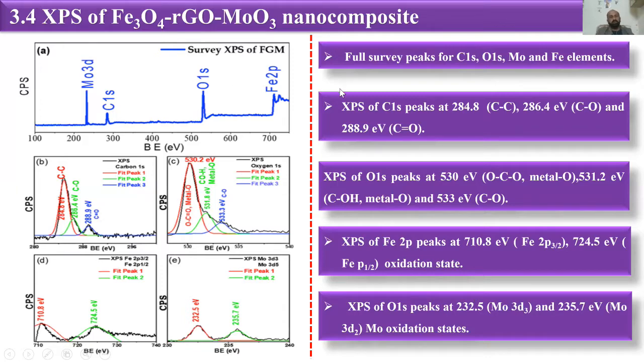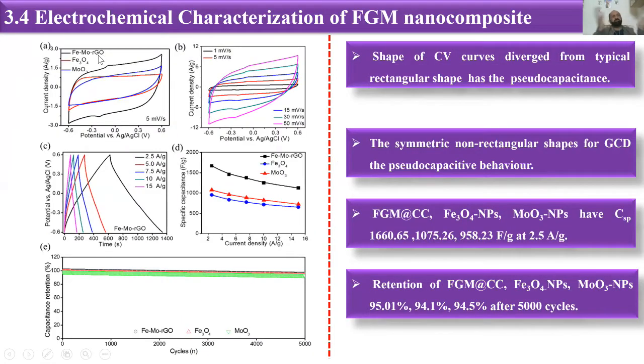We have done the electrochemical characterization. Again, we have done the CV of our FGM, Fe3O4, and MoO3. We have calculated the CV curve for our Fe3O4 and MoO3, and then we have seen the composite of our FGM, and we have seen that the capacitance of our FGM system was about 1660, which was quite remarkable as compared to the other materials. So we have seen the GCD curves for our FGM system, which were also very good.